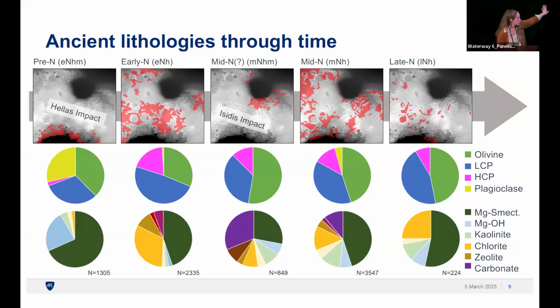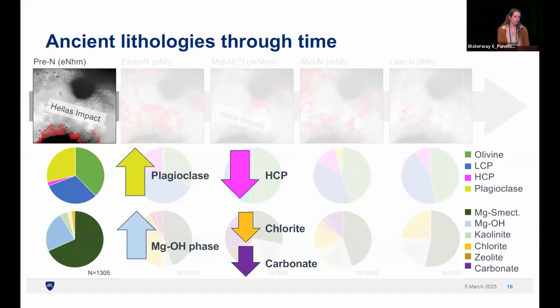The upper pie charts represent the primary lithologies that we've identified, and the lower pie charts represent the alteration mineralogies that we've identified in these terrains. And so I'll start with the pre-Noachian age material, or the material in the early Noachian Highland Massif unit. I'm highlighting here with the arrows how it differs from the other periods. So in the pre-Noachian, we have an enhanced plagioclase signature and an enhanced MgOH phase, which is a dehydrated phase and very different from a magnesium smectite signal that we see all throughout the pre-Noachian and into the Noachian. That's shown in the dark green color, so I won't really reference it because it's pretty comparable between the ages.